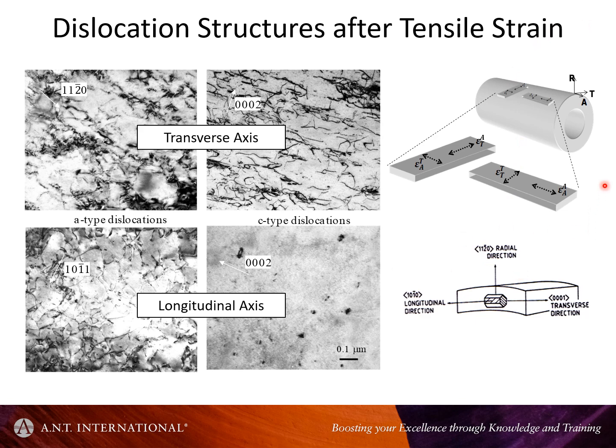So when a material shears, it does so by creation of dislocations. And the type of dislocations you get in zirconium alloys depend on the shear plane and the shear direction. So if your shear direction is inclined to the basal plane, like you want to deform, either elongate or compress along the C-axis, you get one type of dislocation, which is called a C-component dislocation.